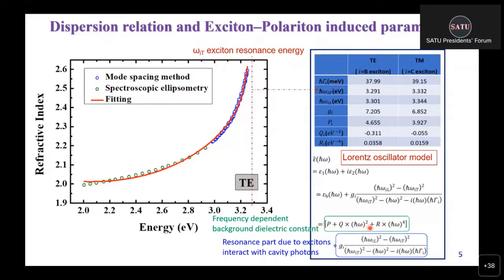The Lorentz oscillator model can be used to extract optical parameters such as the damping term, the resonance energy, or the G parameter. This parameter is proportional to the oscillator strength of the material. When semiconductor excitons strongly couple with the cavity photons, this resonance part makes the response of the dielectric constant become bigger if the energy of the photons approaches the resonance energy of the excitons. We call these quasi-particles exciton polaritons. If the coupling strength equals 0, we can just assume these parameters equal 0, and the observed response reduces to the background dielectric constant only.